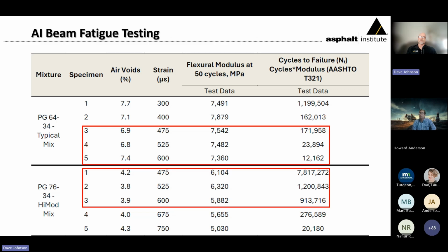And look at the incredible difference in the performance, somewhere around a 70-fold change in the number of cycles to failure at these respective microstrain rates. So it is a significantly different material, because that 64-34 material has performed very, very well and is a proven commodity in the state of Utah. And this 76-34 binder, low air void mix is blowing it away.